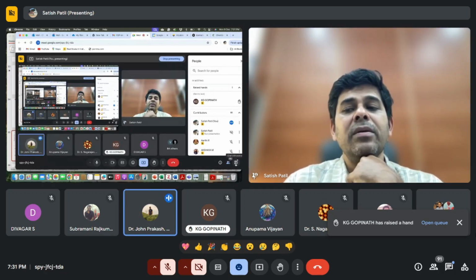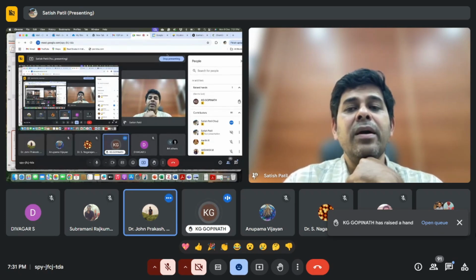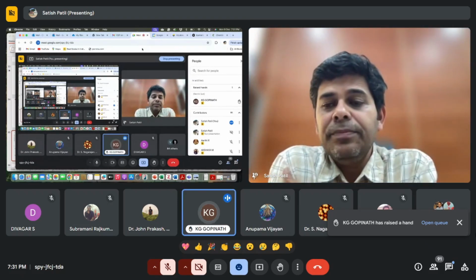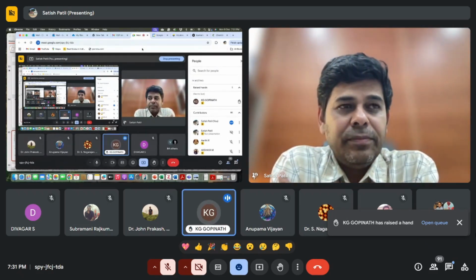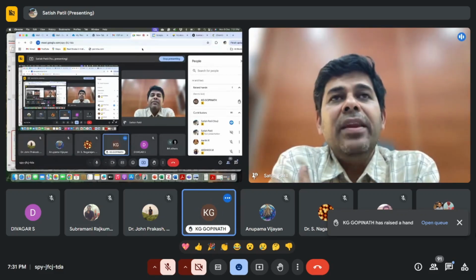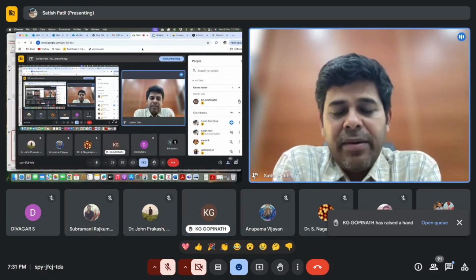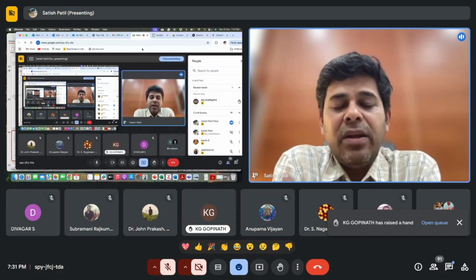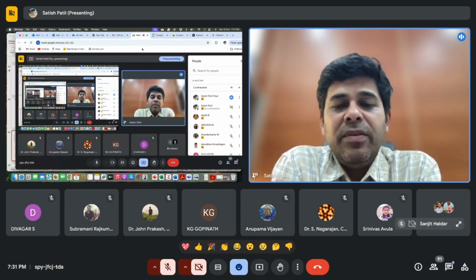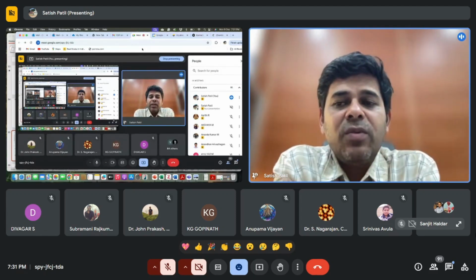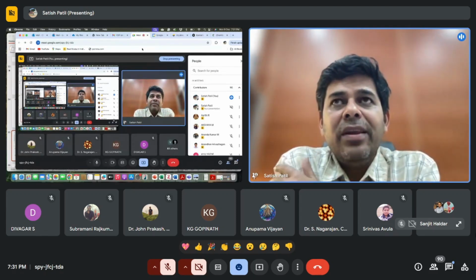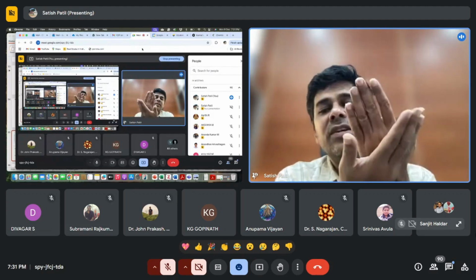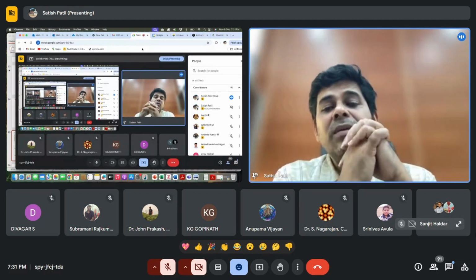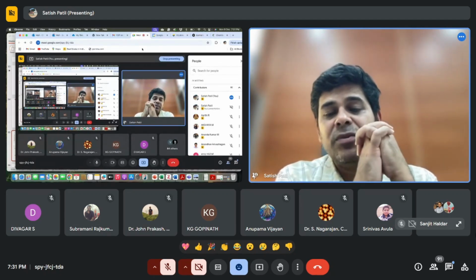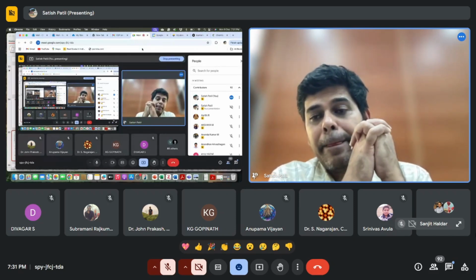One question from Gopinath. Mr. Gopinath, you may ask the question. Instead of fullerenes, how does it play with graphene or graphene oxide? Graphene and graphene oxide will phase separate because these are two-dimensional materials. When you mix them with polymer, the major problem is phase separation. You don't want any phase separation because you want to form a bulk heterojunction. Fullerenes form a very good bulk heterojunction. Graphene and graphene oxide sheets will phase separate from the polymer, so you don't see much of an interface between P and N type. So they do not really work very well. Okay, thank you.